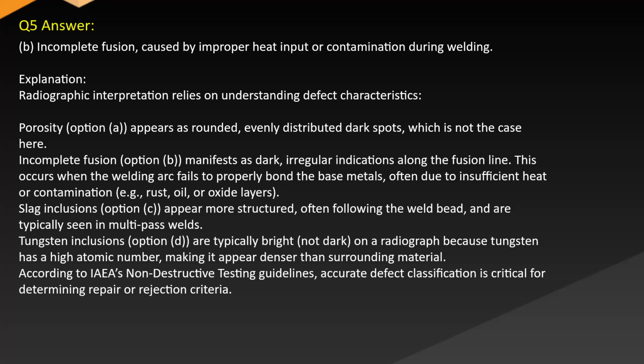Slag inclusions, option C, appear more structured, often following the weld bead, and are typically seen in multipass welds. Tungsten inclusions, option D, are typically bright, not dark, on a radiograph because tungsten has a high atomic number, making it appear denser than the surrounding material. According to the IAEA's non-destructive testing guide, accurate defect classification is critical for determining repair or rejection criteria.